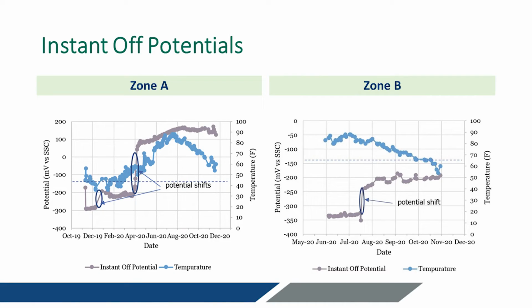And you can see over time how they change based on the temperature. And the blue line is temperature, by the way. So we always want to calibrate because temperature will change those values. But you can see here, we're in a corroding state, and then when the steel's finally passive, it jumps quite significantly up into a non-corroding state. And so that's what the battery is intended to do, is put a lot of charge in to passivate that steel, and when it goes passive, we see this jump in the potential.